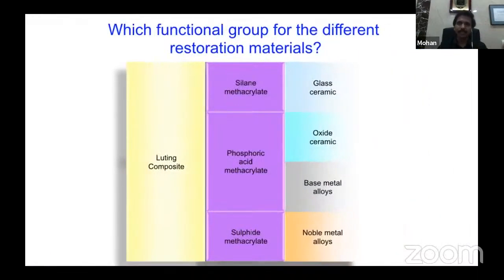So silane methacrylate is always related with glass ceramics, Empress and Emax, and then oxides, that is zirconium oxide, and base metals will require phosphoric methacrylate. So these methacrylates are very important, like a bonding agent. After your surface treatment is over, you apply onto them and then you put your composite on top of it. So this is very, very important so that we are able to do that.